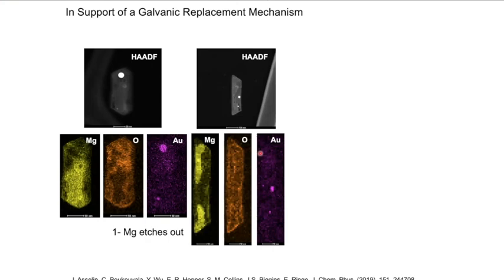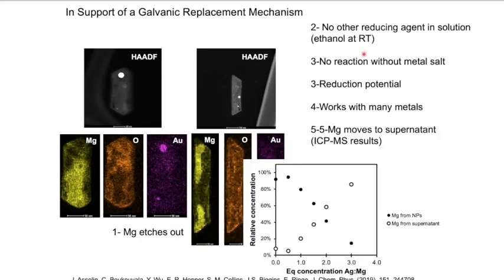But here's the deal. We really think it's galvanic replacement, because we see a lot of etching out and a lot of inhomogeneous etching out of the magnesium where there is, say, a gold particle. We also have no other reducing agent in solution. This is ethanol at room temperature. It will not reduce a gold salt or a silver salt by itself. If we don't put a metal salt and we just put our particles in ethanol, well, nothing happens. They are stable for years in that.